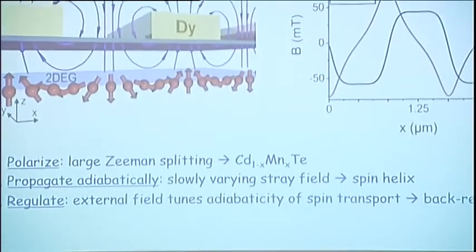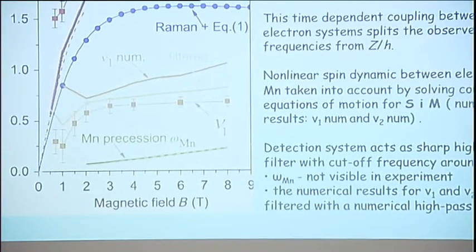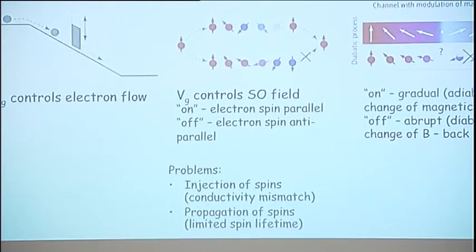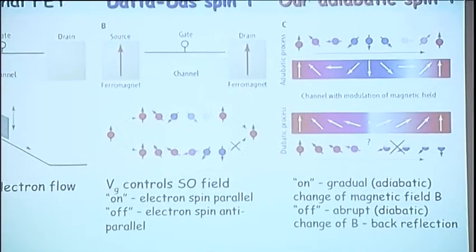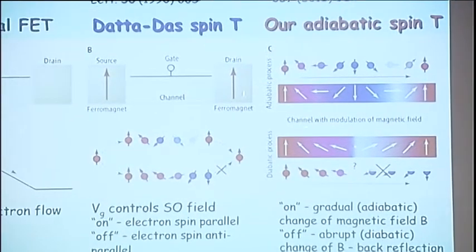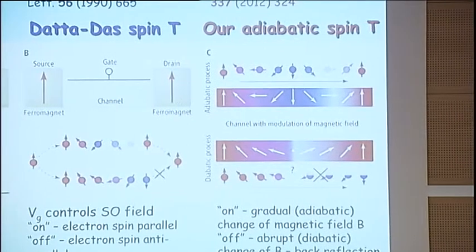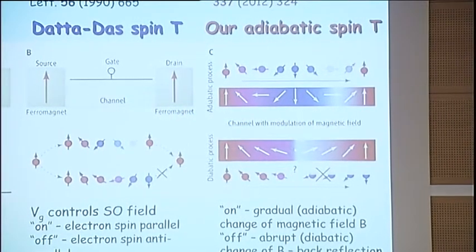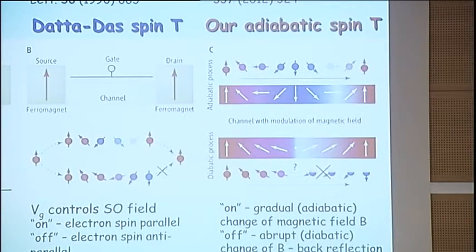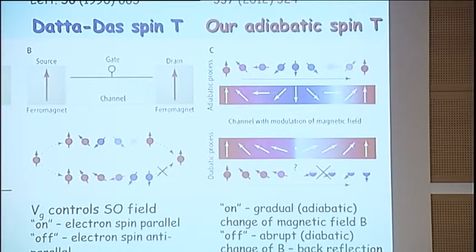But there were problems with this design, because of not very efficient injection of spin, and even more severe, the limited spin lifetime. So the adiabatic transistor that is proposed uses a gradual change of the magnetic field to produce a helical magnetic field, so that electrons moving from source to drain will be able to adjust the direction of their spin, and there will be no obstacle to the transport of the spin. Now, if you produce a sudden change of the direction of the magnetic field, the spin of the electron cannot adjust to this sudden change. It will backscatter, and the resistance will be large.